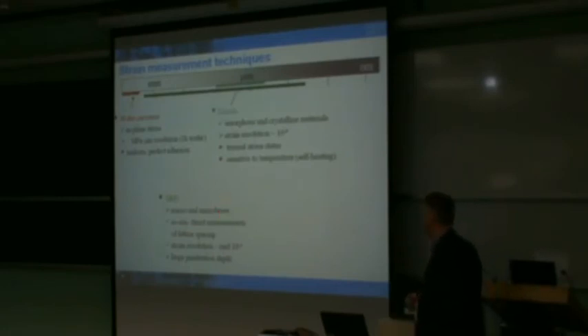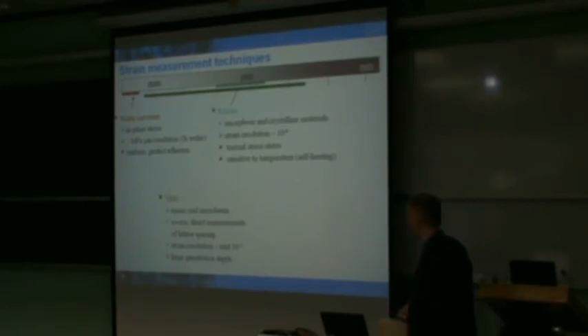X-ray diffraction, I mentioned earlier. It spans a wide range of lateral resolution because there are different approaches: laboratory-based systems, which can be macro beam in size, and those that look at much smaller areas. The nice thing, again, is a direct measurement of the lattice spacing. It's in situ, it can be used non-destructively, and you can interrogate varied interfaces. It has, in many cases, superior strain resolution, 10 to the minus 5 or so, and depending on the application, you can have a fairly large penetration.